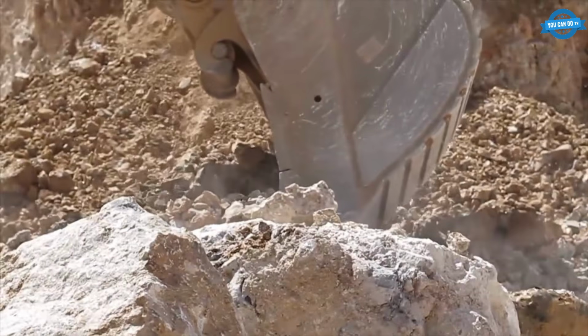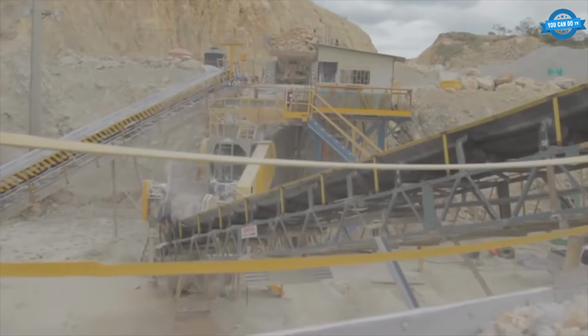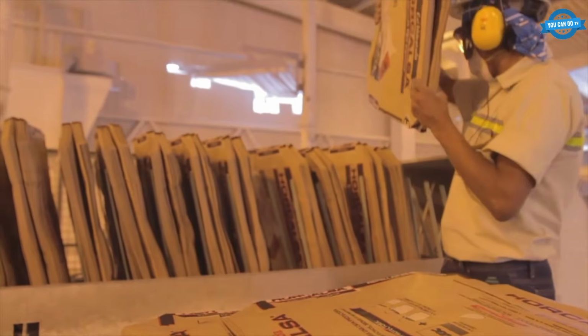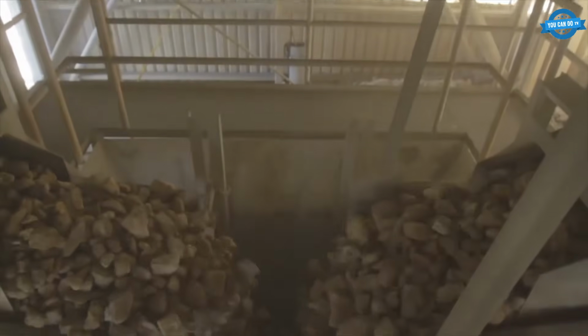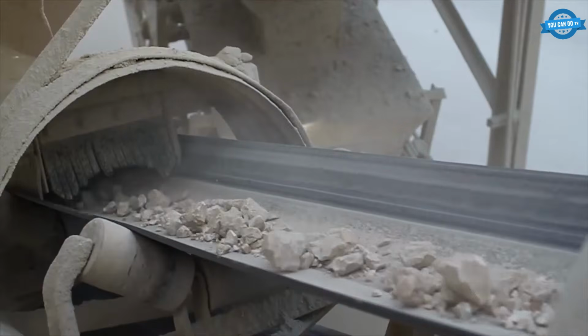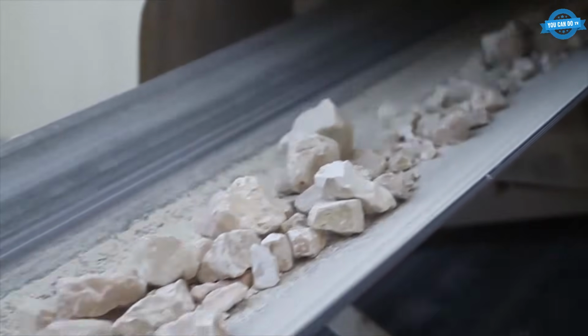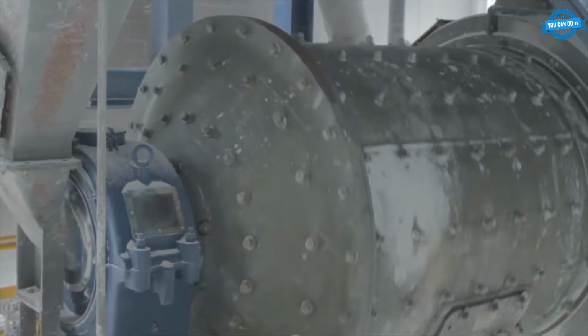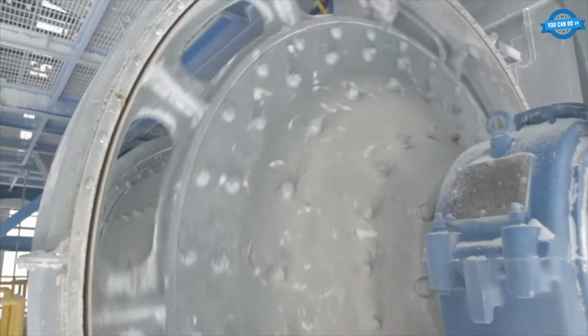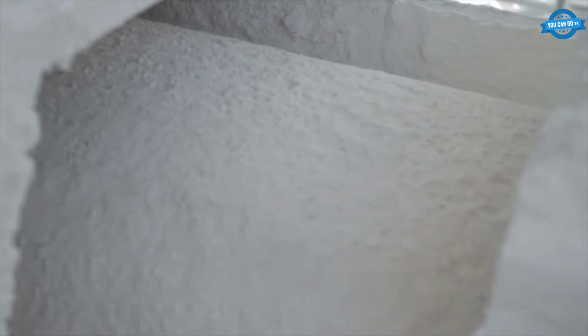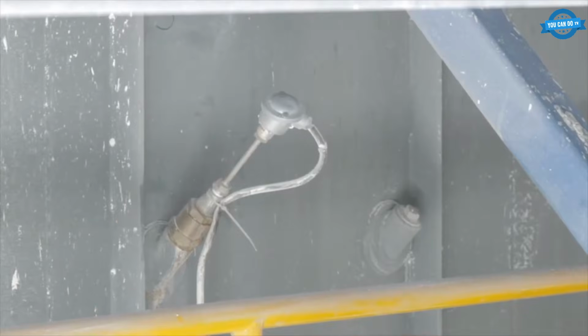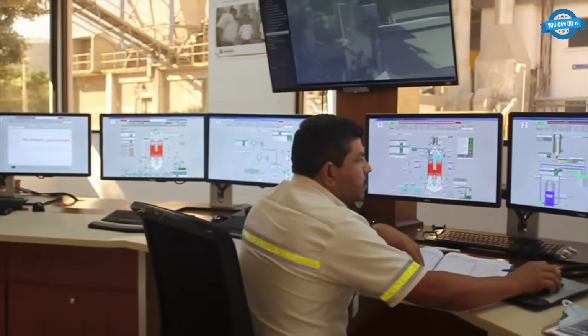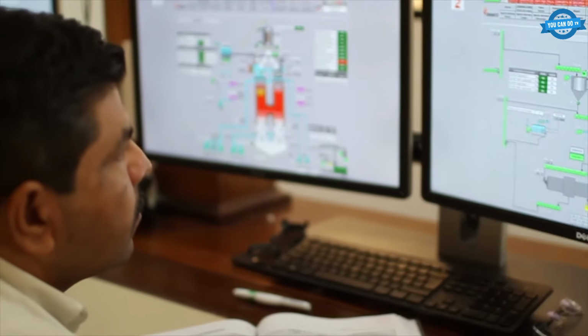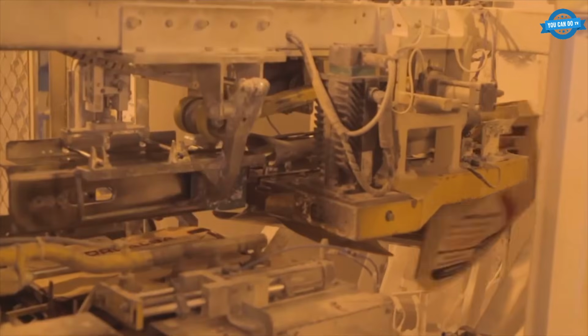The last stop before the product leaves the plant is the one nobody films: hydration and packing. Once quicklime drops out of the kiln, it goes into a hammer mill to be sized down, then into a series of mixers where water is added under controlled temperature and pressure. That reaction is violent. Quicklime plus water releases so much heat that adding too much water too fast will boil it right out of the mixer. 6 minutes of residence time inside the hydrator, monitored step by step, is what turns quicklime into calcium hydroxide.